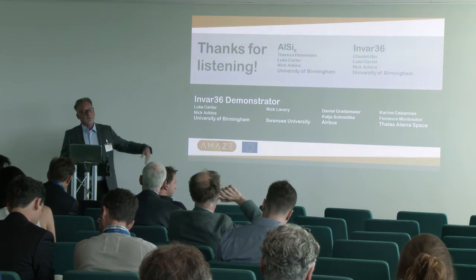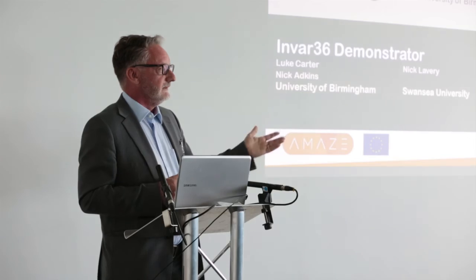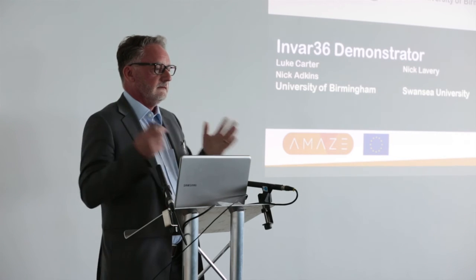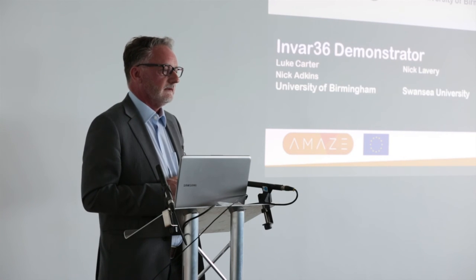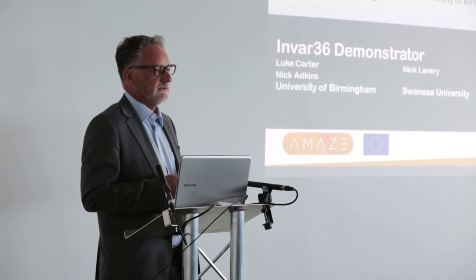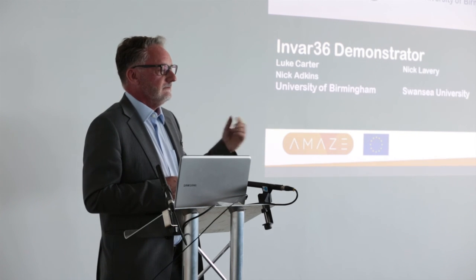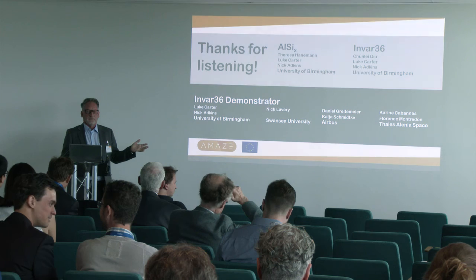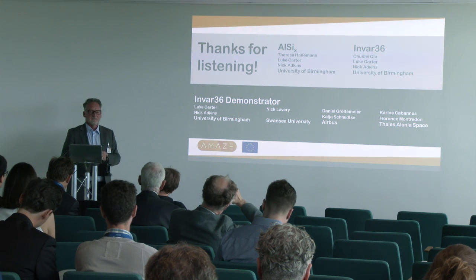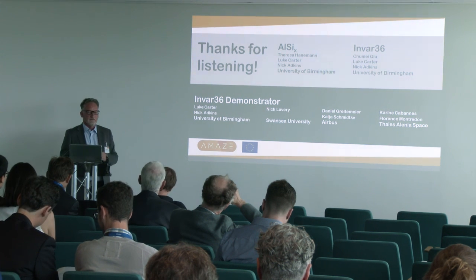And to go past 40 weight % as an addition. A lot of the interest in the aluminium silicon material would be at almost 70% silicon. That's where the thermal expansion starts to match the carbon materials and things. But you can imagine that at the moment Invar is used in satellites, and although it has a density of 8, this has great potential for bringing that down and being more useful.